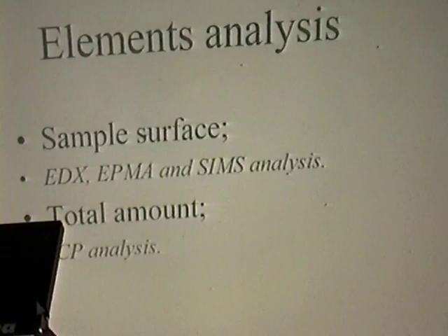Material in the solution and deposition at the bottom of the cell were calibrated by ICP analysis. The element on the electrode surface was analyzed by the EDX. The element was then melted by an acid and calibrated by ICP method.